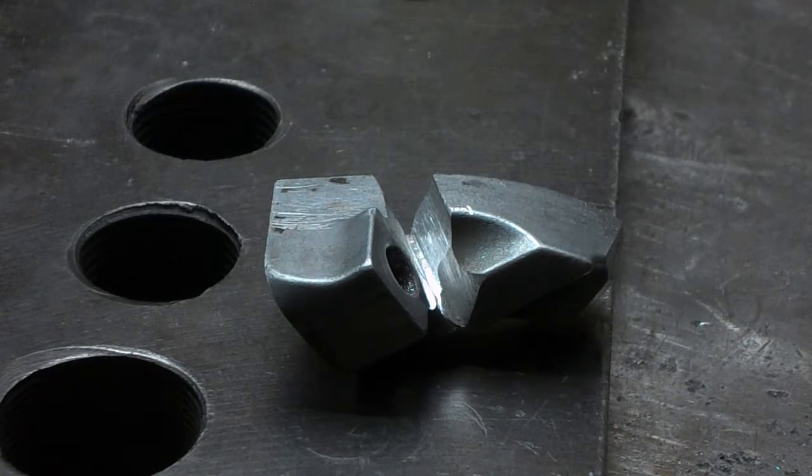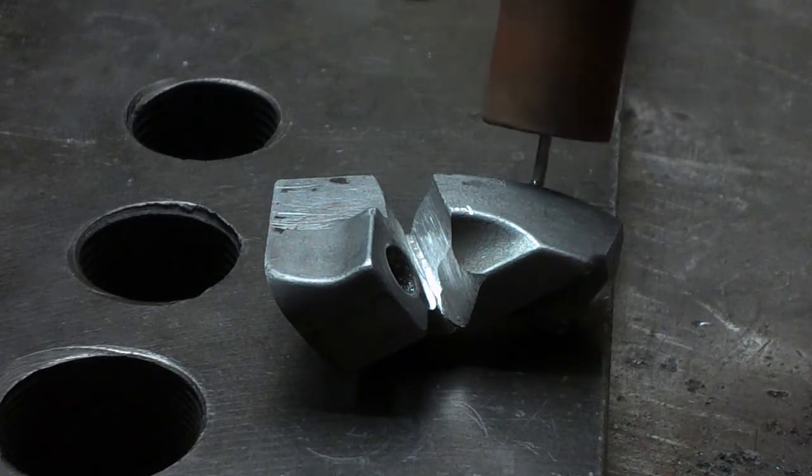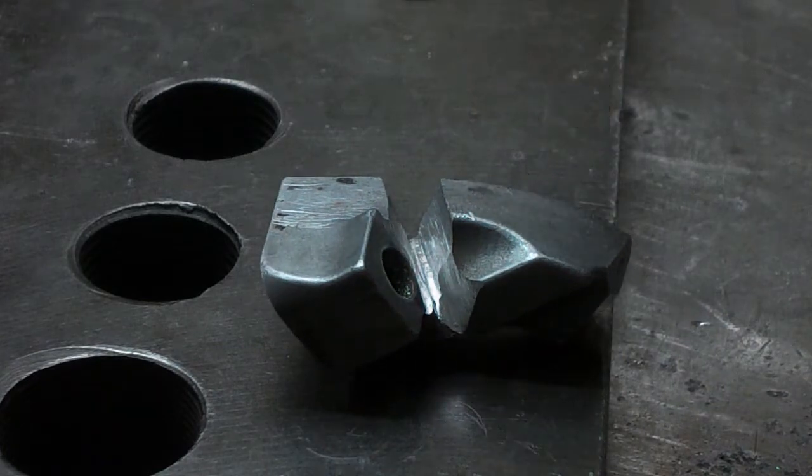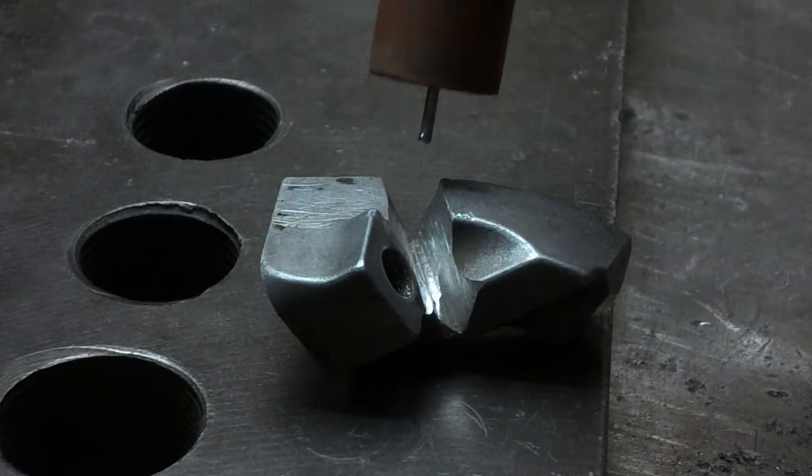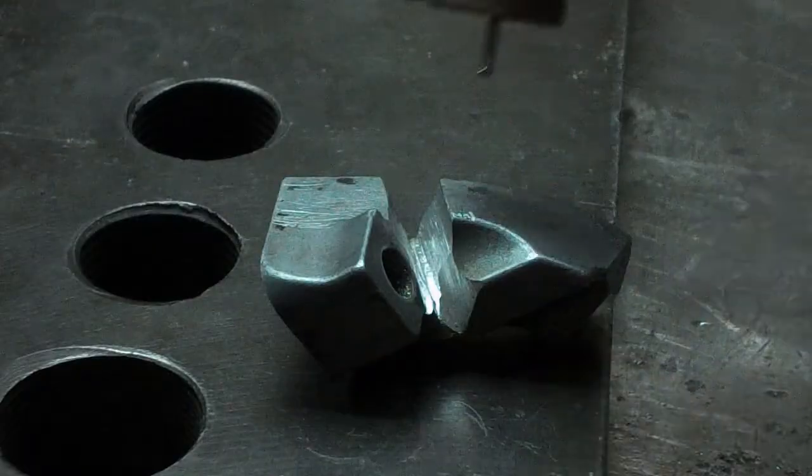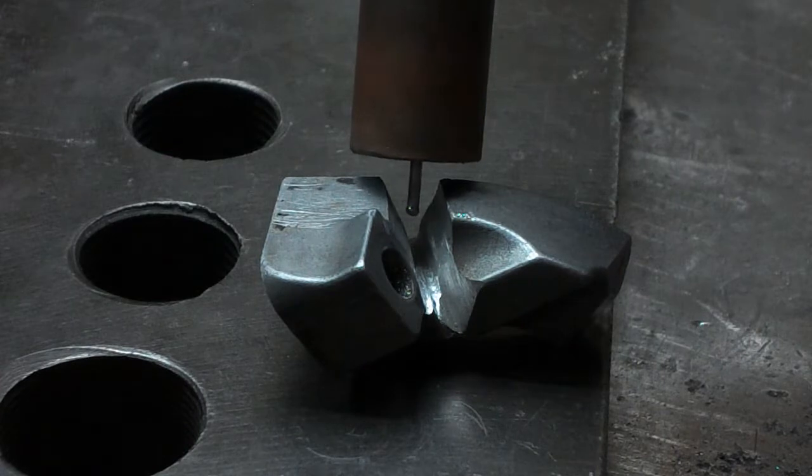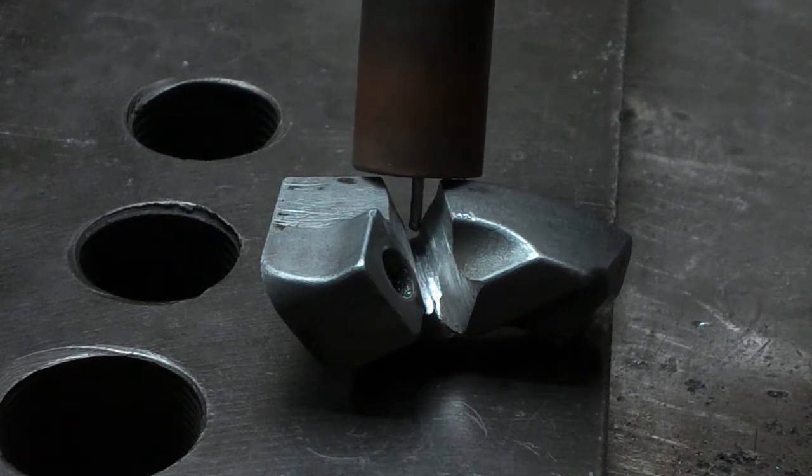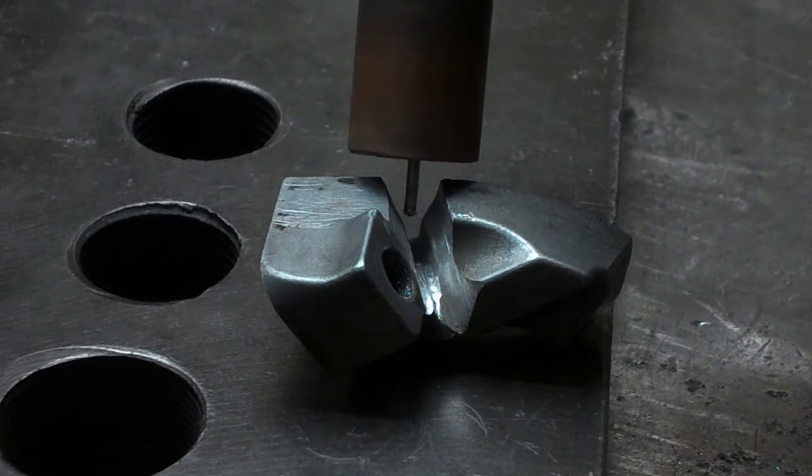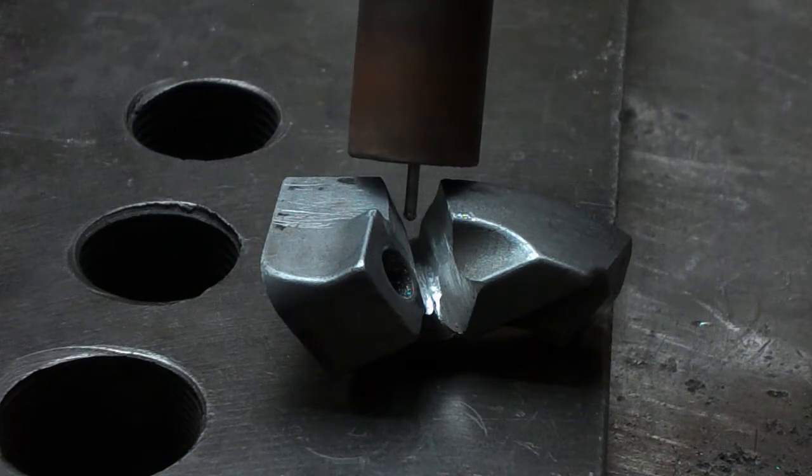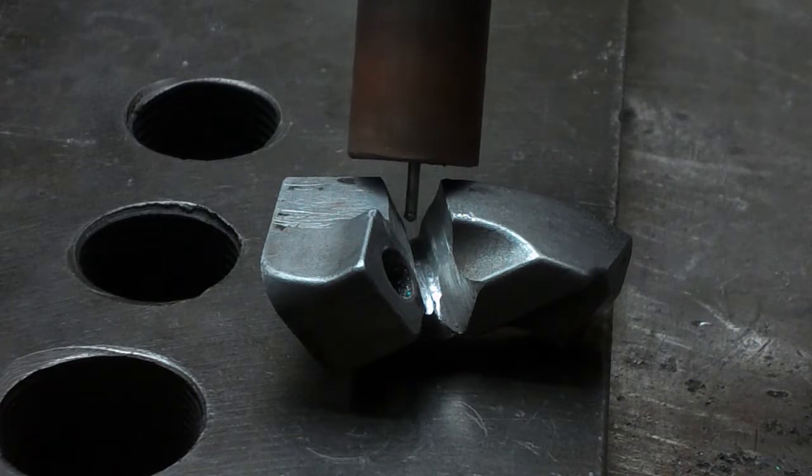I don't know how I'm going to get on here because this is a really deep groove in this piece. Normally if there was a crack here you'd groove halfway on one side, halfway on the other side, but I want this to pull in on the top so I've got to get right down there. That's a crazy amount of stick out. I would never normally have that much stick out on the tungsten. It's going to be so easy to touch it down to the job. Am I going to get enough gas going in there? I do not know.